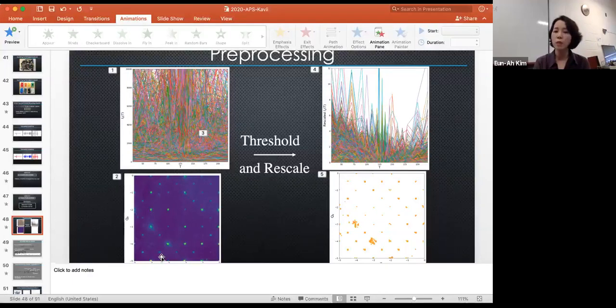And because human eye inspection is very time consuming, you would try a couple of slices, and if you find what you were looking for, you'll be satisfied. It's very hard to discover what you were not looking for, because there's no way you can exhaustively search this data. As for the intra-unit cell distortion, it is extremely difficult with X-ray, because any intra-unit cell changes are only reflected in the form factor or the phase of the peak. And if you have a really sharp peak, there will be no structure visible.